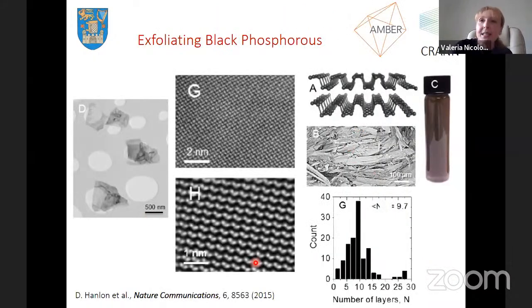A very, very interesting material that we more recently managed to exfoliate is black phosphorus. Black phosphorus has been getting a lot of attention because it has extremely interesting electronic properties similar to graphene. The downside of black phosphorus is that it degrades extremely fast and easily in presence of oxygen. So what we actually showed was that, yes, by liquid phase exfoliation, we can indeed exfoliate raw black phosphorus, and we can get few-layer sheets, and their atomic structure is nice and pristine.